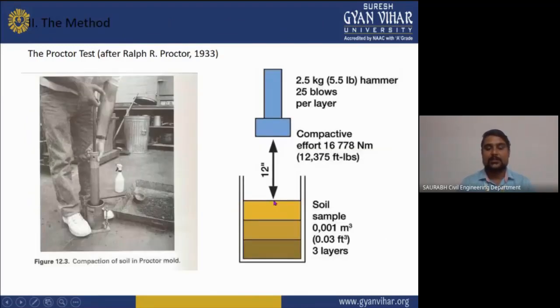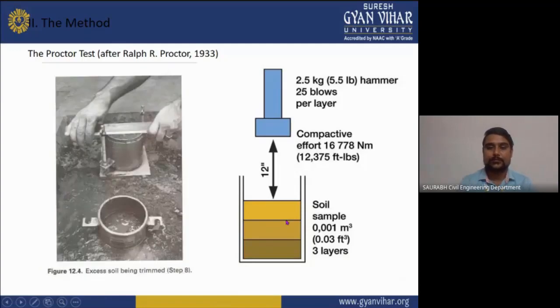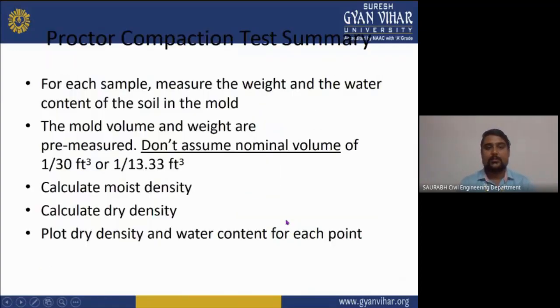This method was invented by R. Proctor in 1933. As you can see, the soil is divided into 3 layers, and we use a 2.5 kg hammer, giving each layer 25 blows of the hammer. Now, in the Proctor compaction test summary, for each sample we measure the weight and the water content of the soil in the mold. The mold volume and weight are pre-measured. Don't assume the nominal volume of 1/30 cubic foot or 1/13.33 cubic foot. Calculate the moist density, calculate the dry density, and plot dry density against water content for each point.